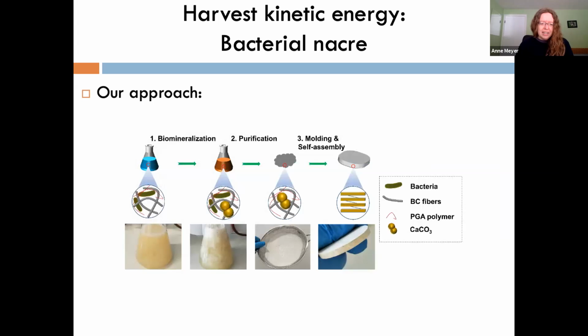So here's our approach. We take that thick layer of cellulose, which is very inexpensive. We bought a kitchen blender, throw it in, and blend it up. Then we put it in our flask and mix it together with the bacteria. Over time, the bacteria make crystals of calcium carbonate that stick to the fibers of the cellulose. We let it start growing and making crystals, then we put it into a mold of whatever shape we want. And then it gets very stiff as the crystals develop, so we end up with, in this case, a little tablet of stiff cellulose-based nacre.